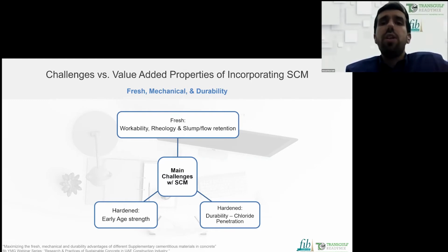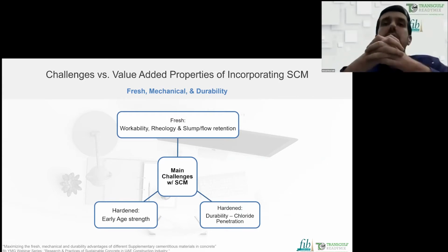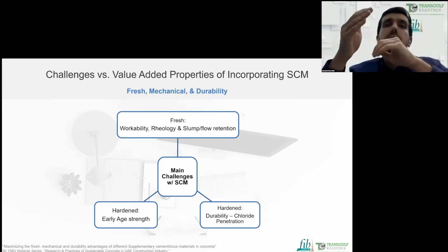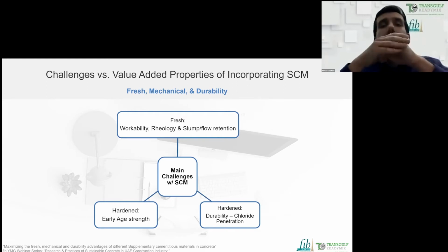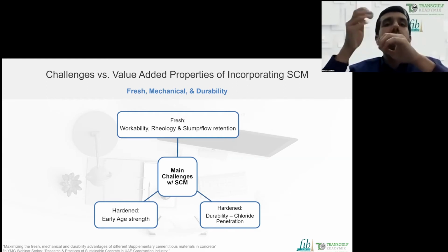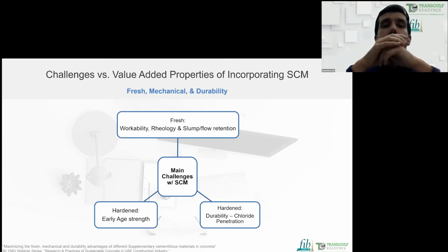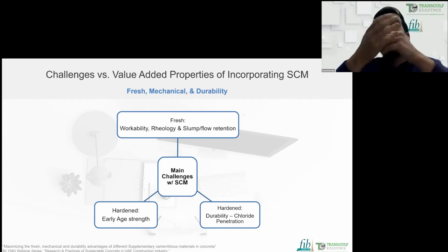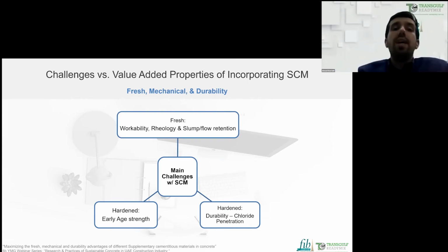Actually, here we know that we usually face challenges when incorporating supplementary cementitious material. It depends, of course, on the concrete mixes, the type of supplementary cementitious material, the percentage of replacement, and other parameters like the water cement ratio. So the main challenges that I'm going to highlight are the fresh properties: workability and rheology, slump flow retention. And on the other side, the hardened properties like compressive strength, where with supplementary cementitious material we usually face an early age delay in strength. It depends, of course, on the design.